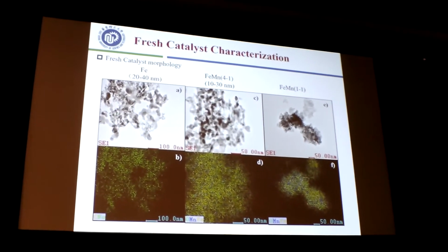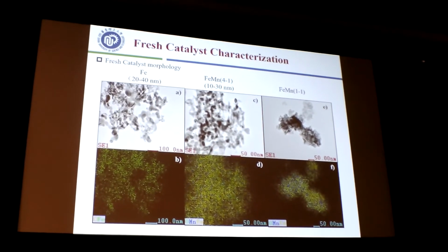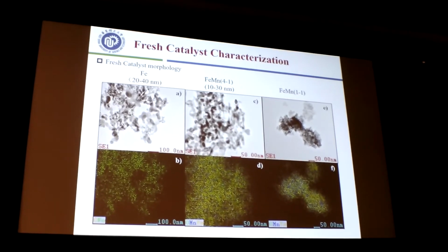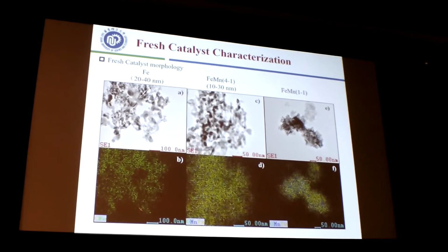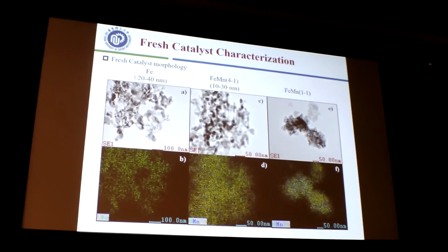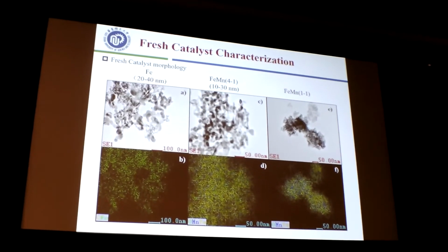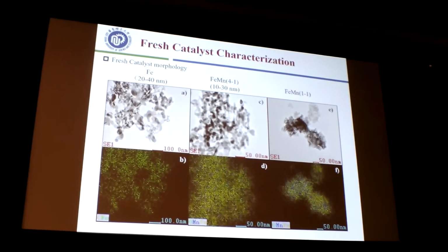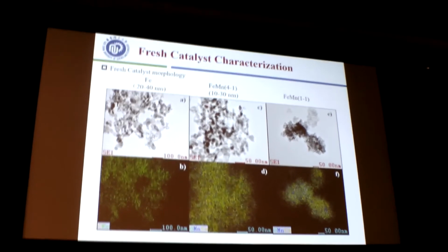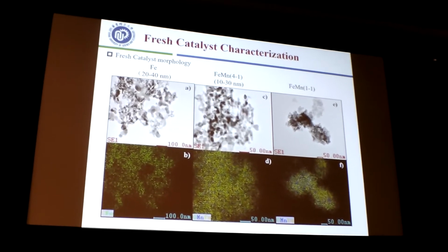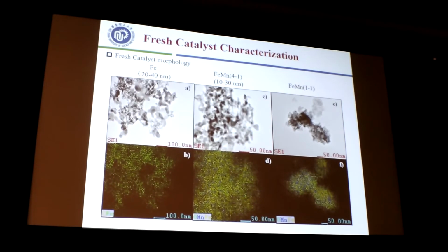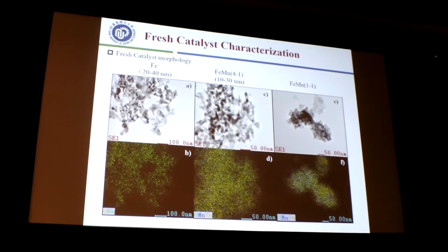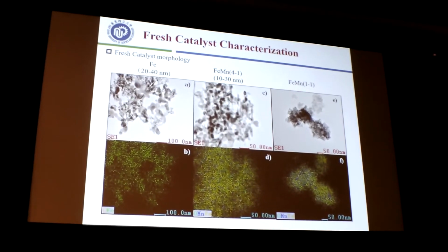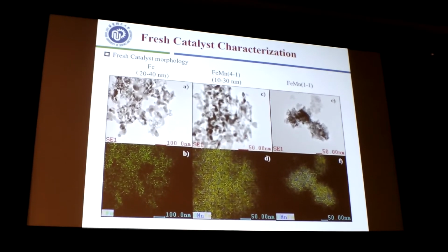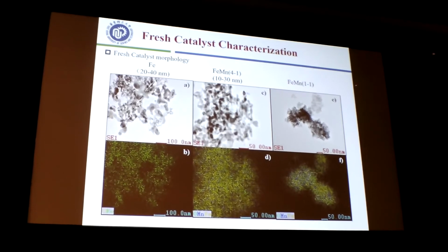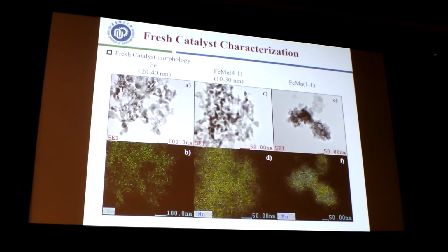And then we used TEM to observe the morphology of the iron particles. Here it shows 3 different catalysts: the single iron, iron to manganese 4 to 1, and iron to manganese 1 to 1. We can observe that the single iron catalyst has a very good crystallinity degree with a particle size of 20 to 40 nanometers. As we increase the manganese loading, the particle size decreases. But if we further increase the manganese loading to 1 to 1, then the crystallinity degree decreases, which means that excess manganese loading can decrease the crystallinity of the iron nanoparticles.